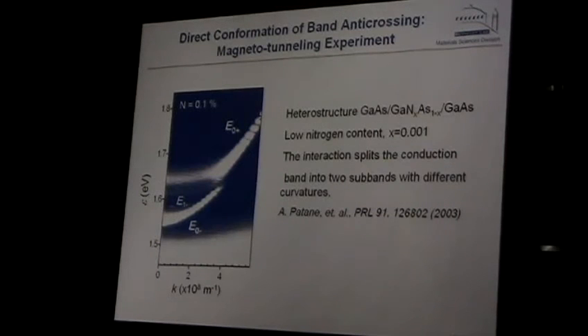In the meantime, some other people got involved in this, and they showed that it's really what's happening. This is a very low composition, only 0.1%, but you see these nitrogen levels are already cutting the conduction band into two parts, the lower band and the upper band. In a sense, it forms a separate new band here. Not so narrow a band, but a separated band.